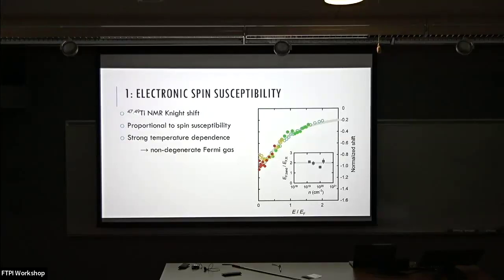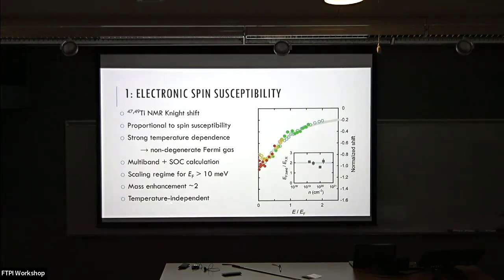Do I understand you're basically taking the band structure and squeezing it by a factor of 2 and then everything works? Exactly. The main point is that it works at finite temperature. Yeah. This is a temperature that's comparable to the Fermi energy. So it's not just a low temperature mass, it's across the whole range. And this is a unique thing that you can get from NMR. So it's a local susceptibility probe. Okay, yeah, this is basically what they said.